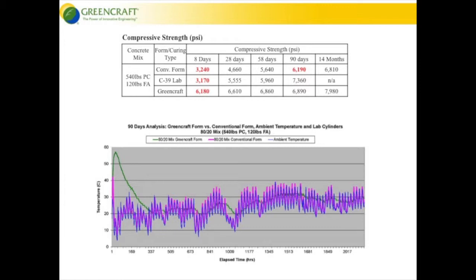And this is a mix with quite a bit of Portland cement, 540 pounds of Portland cement, 120 pounds of F fly ash. That mix will do well in just about any environment. Yet in our insulated form, we get twice the strength at about 8 days that you do in the lab or in the conventional form. At 28 days, 6,600 PSI versus 4,600 PSI. It takes until day 90 to get the same strength of that mix in the conventional form as the GreenCraft form. We've done some coring 14 months after the fact, almost 8,000 PSI.